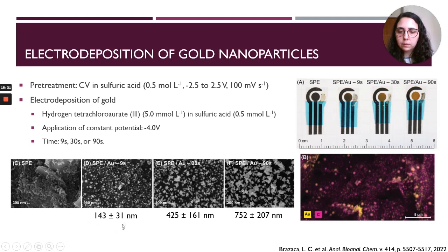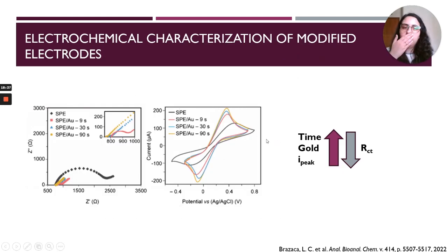We do have a very large increase in the diameter of the particles, from 143 to almost 800 nanometers for 90 seconds. So how does this relate to the performance of the biosensor? But first of all, we did some electrochemical characterization of the modified electrodes. So we can see that with the increased time of electrodeposition of gold, we do see an increase in the peak related to the redox process of ferricyanide, as expected, and we do see a decrease in RCT, showing that we do have more conductive surfaces. So looking at this, maybe it could seem like the 90-second electrode would provide the best performance for immunosensing.